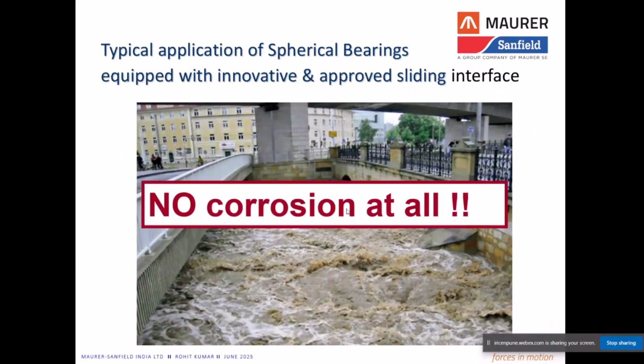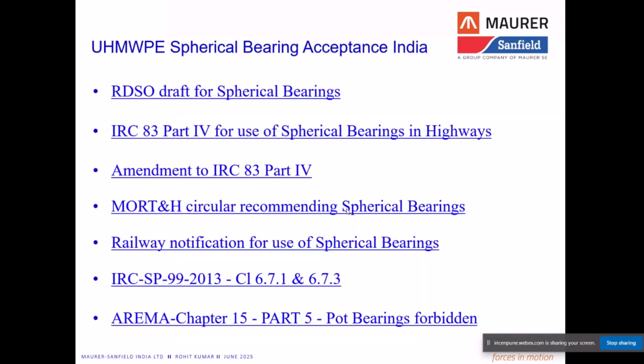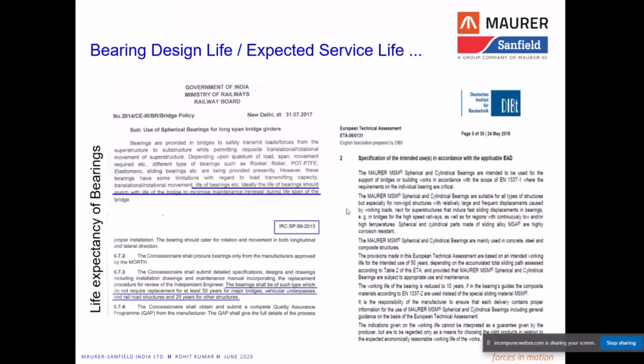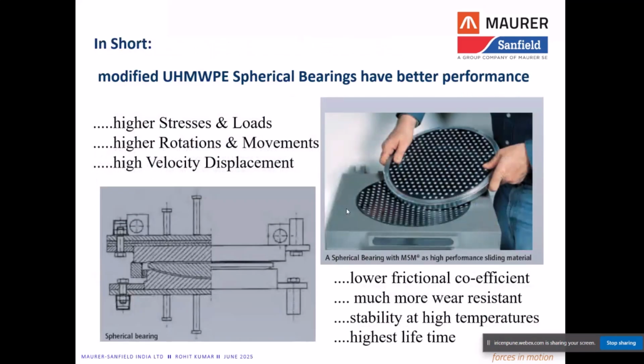So even if there is a very highly corrosive environment, there is a possibility to provide a bearing solution which can fulfill the requirement of the structure. And these advanced materials are accepted in our codes also, in our Indian codes as well as the foreign codes. These are some references of our codes. So in short, by using an advanced material and our oldest technology of rocker roller bearing, these bearings fulfill the requirement of higher stresses and loads, higher rotations and movement with high velocity displacement, providing a low friction coefficient, much more wear resistance, stability at higher temperature, and the highest lifespan.